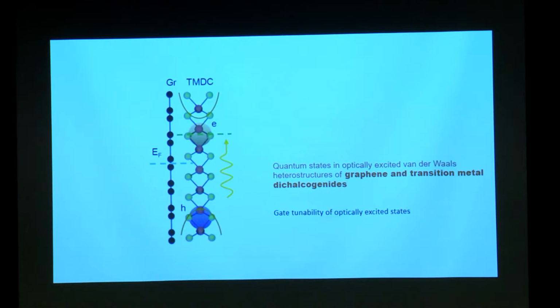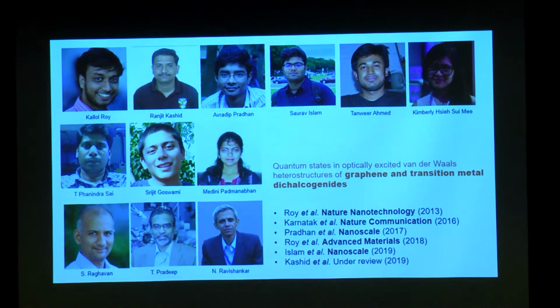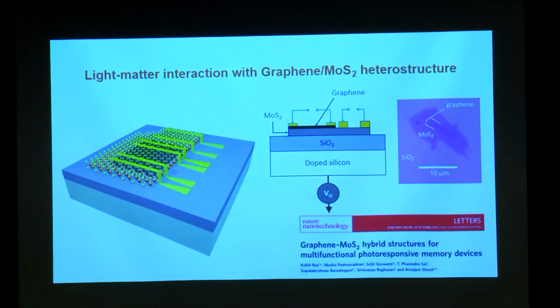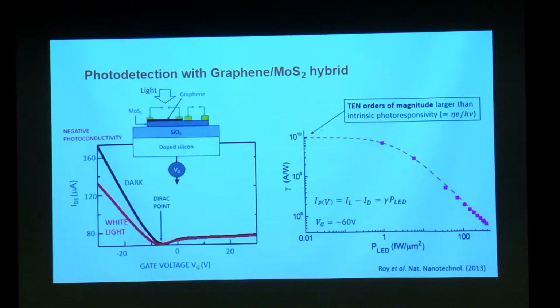So that's the purpose. This work has been done for a while now, and there are a lot of people, my students and my colleagues, who have been involved in this. This work started about 5 years ago, and when we put graphene on chalcogenide and looked at electrical transport in graphene, it gave us some very interesting results, because what we found is if I shine light on the molybdenum disulfide